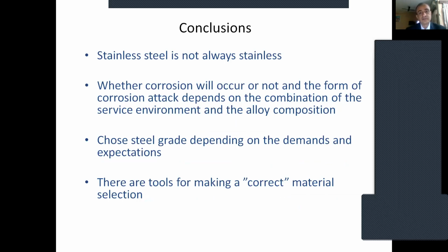Whether corrosion will occur or not, and the form of corrosion attack, depends on the combination of service environment and the alloy composition. So there are environments which cause permanent breakdown of the passive layer. Under circumstances where the passive layer cannot be rebuilt, corrosion occurs on the unprotected surface.